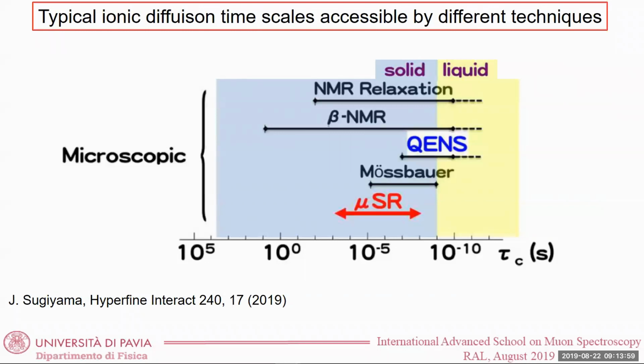What is important when we compare these different techniques is a big difference between local probes like nuclei, muons, and electrons, and non-local probes such as neutrons. The difference is that with the local probes, as we will see in the next lecture in the afternoon, what you are probing is the Q integrated, so the integral over the Brillouin zone of all Q excitations, while with neutron scattering you can be Q selective, and so you can probe each excitation at each Q wave vector at a time. So this is an important difference that I want to report. These general remarks should be taken with some care.